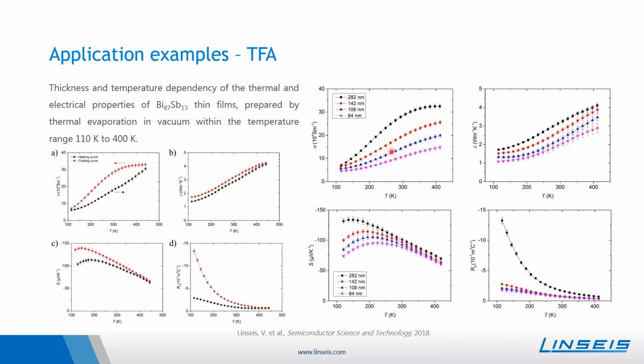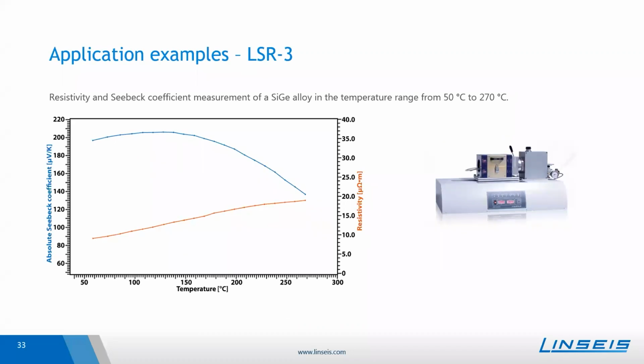Here you can see the electrical conductivity, the thermal conductivity, Seebeck coefficient, and the Hall constant in dependence on temperature. You can clearly see different behaviors of different sized films, and the behavior also changes with temperature. Furthermore, the material behaves differently depending on whether you are heating up or cooling down the material. So with these instruments, a lot of analysis can be done, also testing different requirements. Here you can see a measurement of a silicon germanium alloy measured with the LSR3. A rather bulk sample was used, and clearly the resistivity changes with temperature.